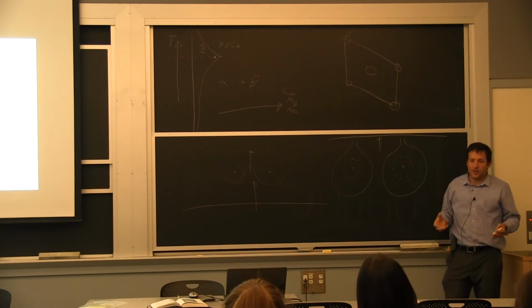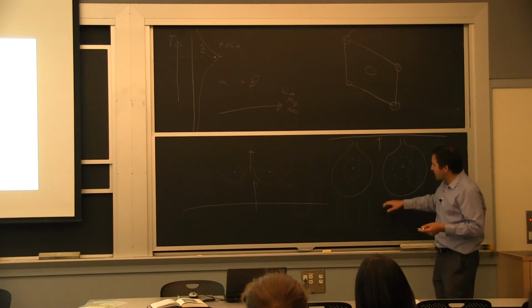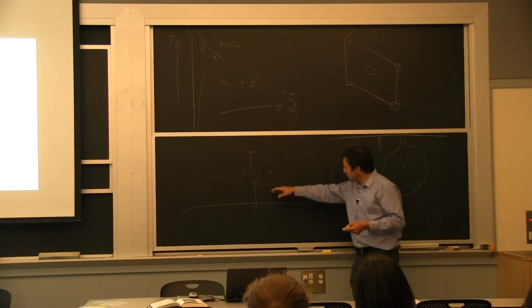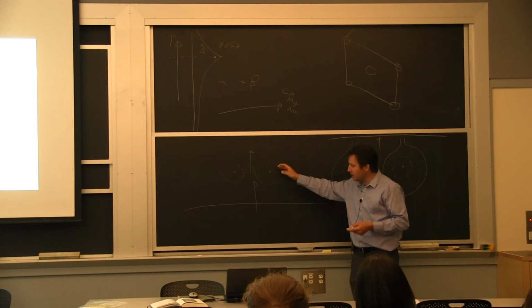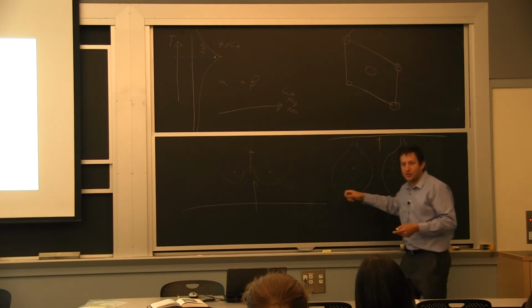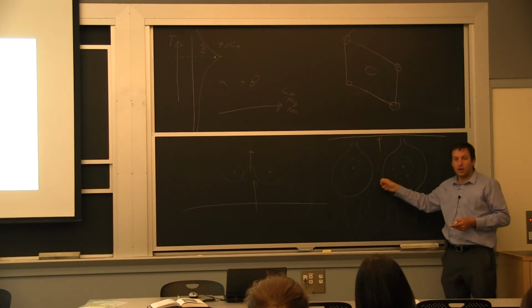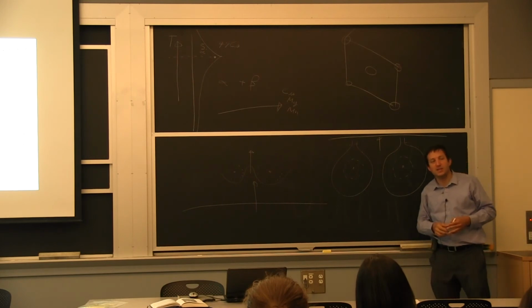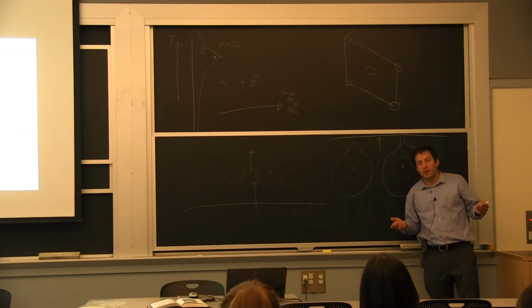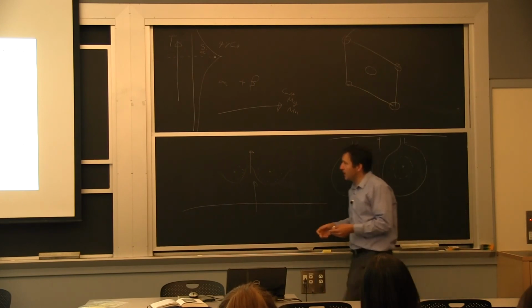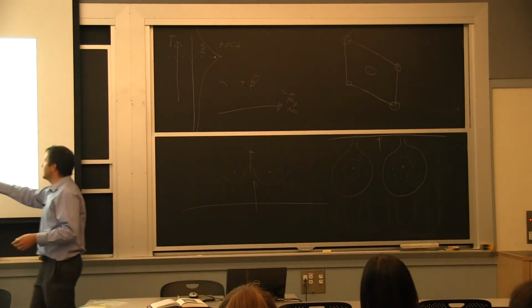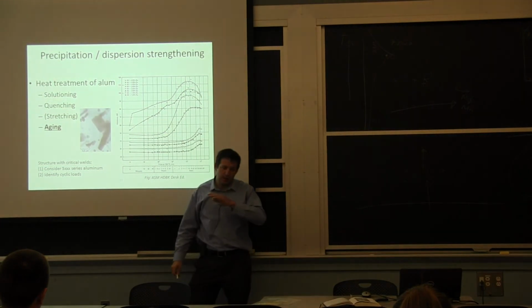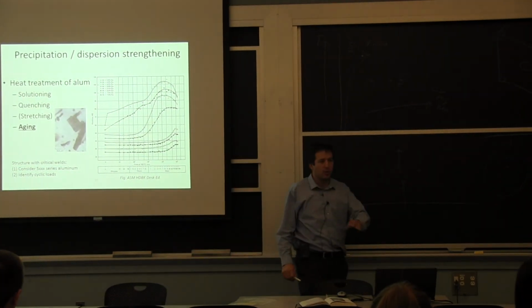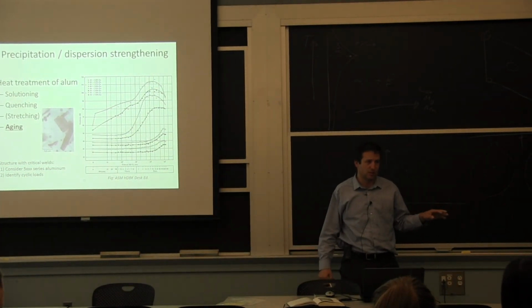An advantage of this type of hardening, and what you should keep in mind, is that it not only affects the initial point where the crystal was relatively clean and I came with the first dislocation. As you go, it becomes harder and harder to go through the precipitates, and that means a lot of hardening. If the precipitates are very fine, like I have here in this micrograph, the dislocations keep going right through them. From one time to the other, it's the same resistance.